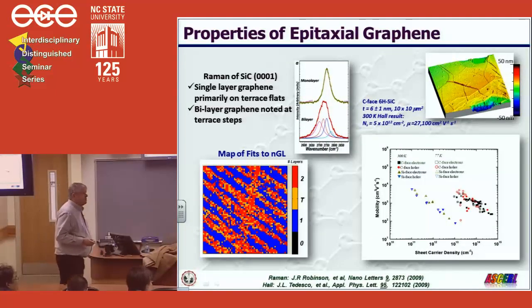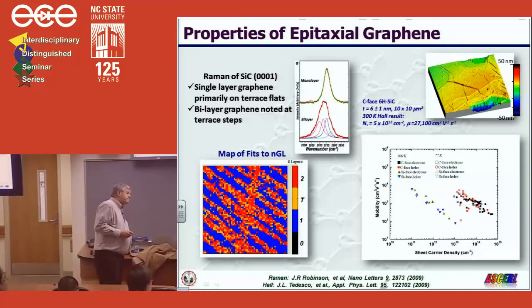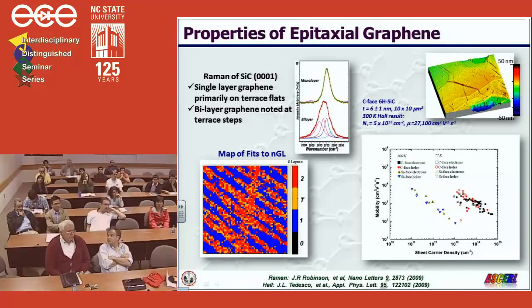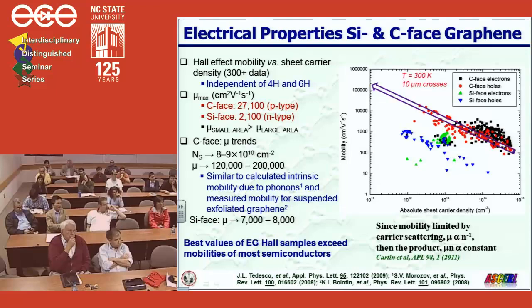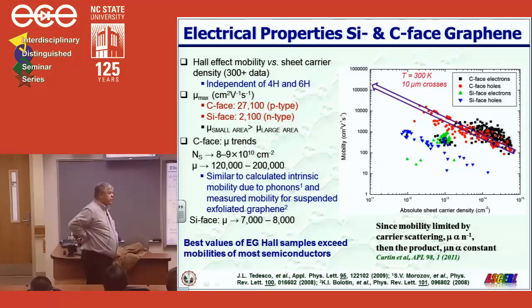Excuse me. Do you understand how to control the sheet density on the two faces? You have these plots. Here's another one. What's different about the different data? They're all at room temperature. It's because they've been treated with photoresists. They've been sitting out in the open. If you're very careful, and we've been trying to exercise this level of concern, you can get the same result all the time within 10%.